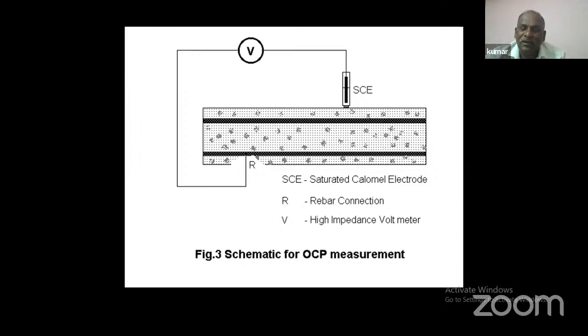Like that, if it is carbonated, you will get different kinds of potential. So on the surface with the different grades, you have to find the open circuit potential and make a mapping, find which are the gray areas that are vulnerable or contaminated with other halide ions or any contaminations. So the OCP is mostly useful to identify, qualitatively, whether corrosion is initiated or not.